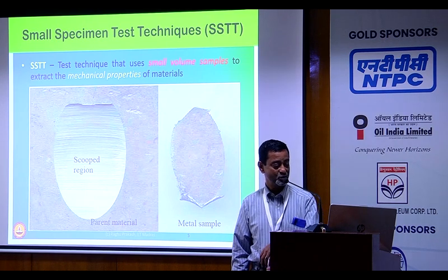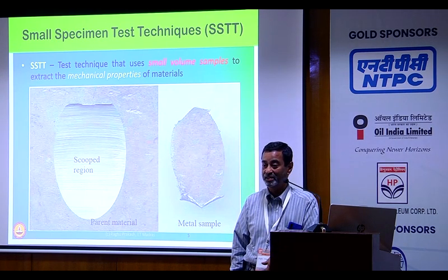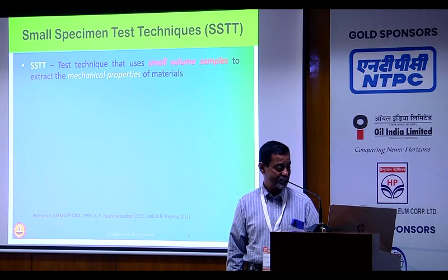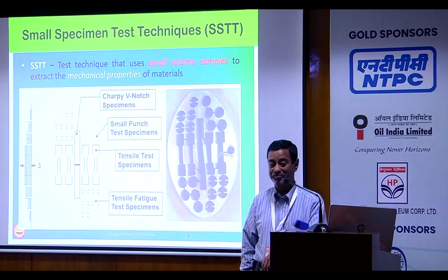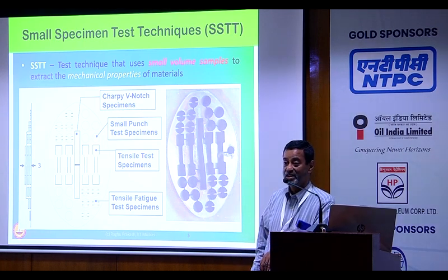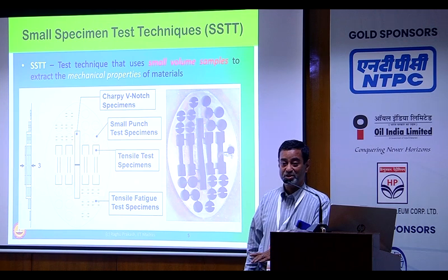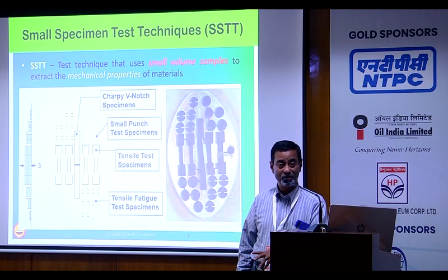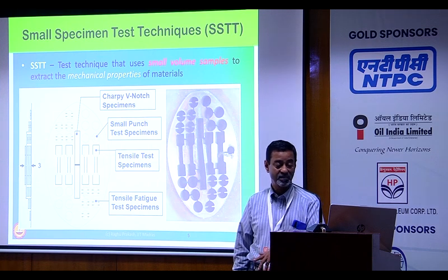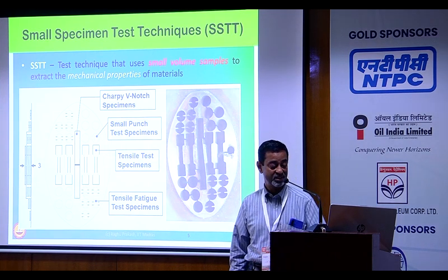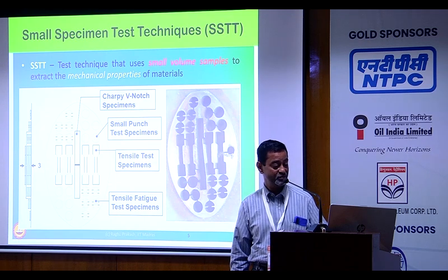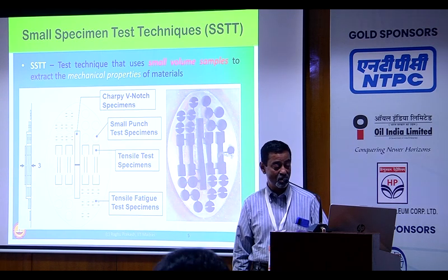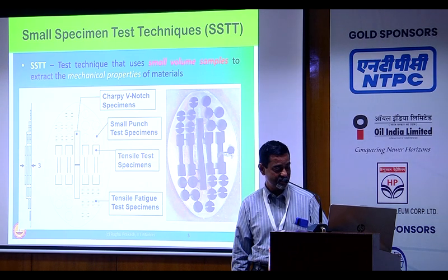See, this is the kind of scooped region and then the scoop material. And from there, we are going to extract so many specimens. They are used for tensile tests and for indirect property measurements like the small punch test, or you use it for the Charpy impact test and so on, and even fracture toughness experiments. So we make so many of these specimens, and what is important is to see how these results correlate with the big size specimens that we use in the ASTM standards.